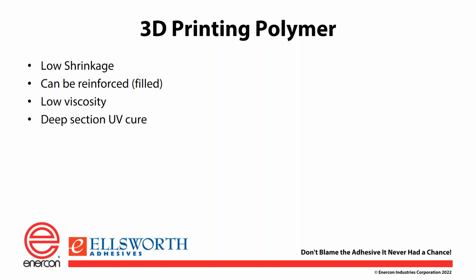So we were tasked with coming up with something that would still fit into a 3D printing process, still use light radiation cure to polymerize, yet they wanted two things. They wanted much lower shrinkage and the ability to put opaque materials into the polymer and still allow a UV cure. So we have come up with a product that does this. It's kind of unique. We need to find a partner for this one, but again, I just wanted to give you a flavor for some of the interesting products that we have going. And the shrinkage in the filled state would be about 1/10 of that of a conventional UV printing acrylic resin system.